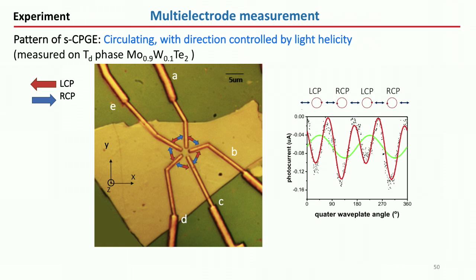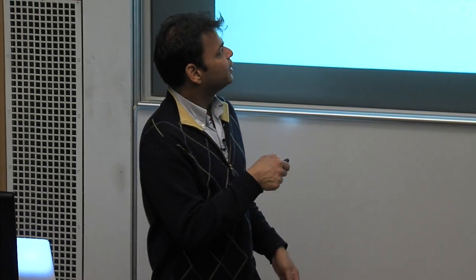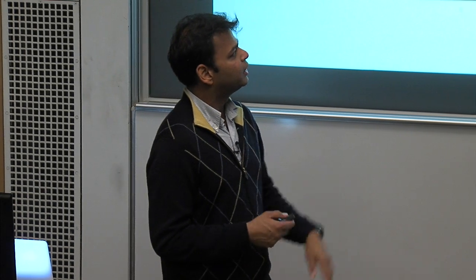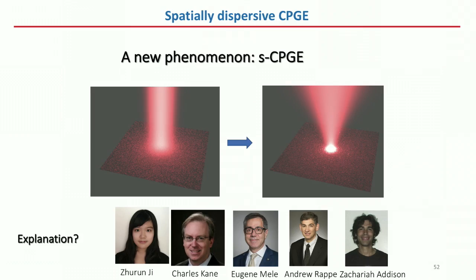So to put the long story short, what is happening, and this is a very unique effect, is that if we shine right circularly polarized light, then the photocurrent actually circulates; it swirls in the direction of polarization. This is very intriguing. And if we invert the polarization, the current swirling direction actually changes. So we have swirling currents tracking the polarization direction of light, okay?